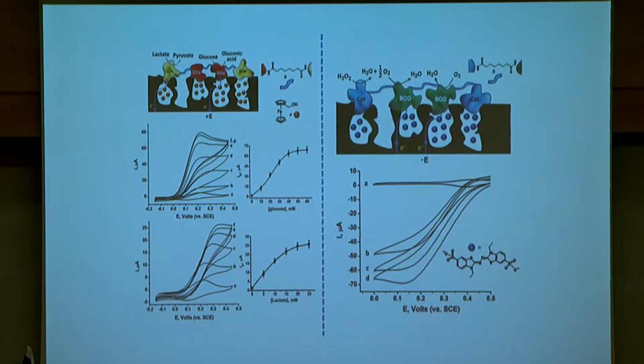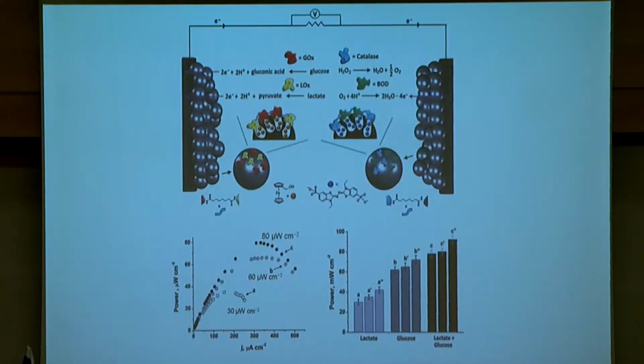You can see here the electrocatalytic activity of the anodes and of the cathode. And once we had characterized these separated electrodes, we combined them to generate a biofuel cell. And you can see here the power output of this biofuel cell when we have lactate as fuel, glucose as fuel, and if we add both systems, we get a substantially higher output that combines the performance of the two elements. So this story briefly summarizes activities to electrically contact enzymes with electrode support and shows you what you can do with this type of biomaterial.